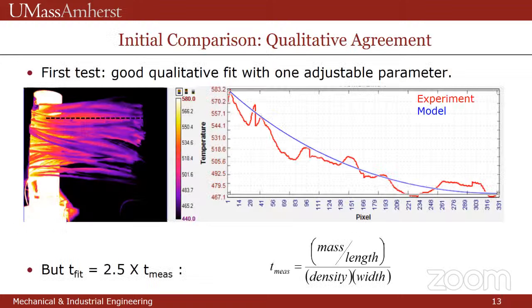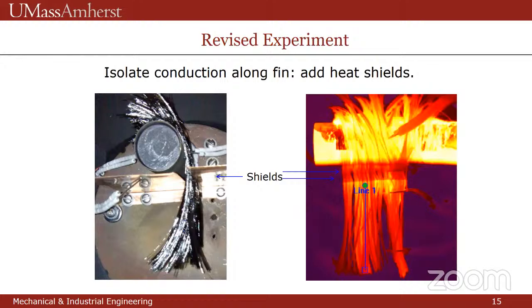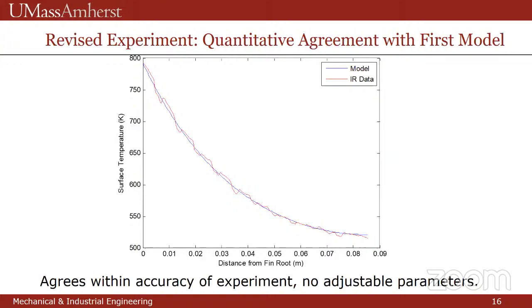So who's right? And we went through the model, compared analytical results. Our model was working, our software was working, everything looked great. We took a closer look at the experiment, and it turns out that that big bright tube has a significant view factor onto the fins. So we're heating the fins by radiation from the heat pipe directly, as well as by conduction. So when you add these copper heat shields, or radiation shields, so that you have only conduction through the fins, then the situation gets better. And here we've got the fit of the new experiment against the original model with no adjustable parameters. And it goes right through the middle.